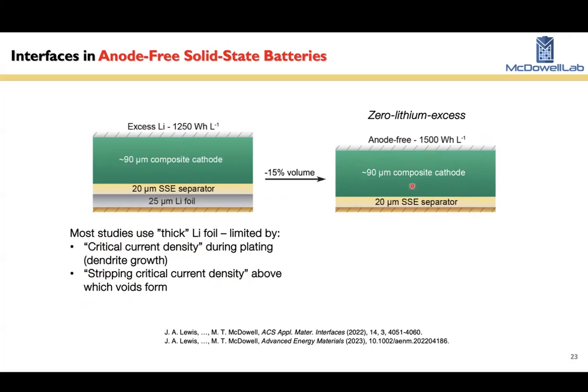And on the first charge of your cell, you move your lithium ions down to the anode and you reduce them and plate out lithium metal on a current collector. The reason why you want to do this is because it can result in higher energy density. You have minimal material at the anode, and so it's commercially very attractive. So the question we asked is, if we move from this scenario to this scenario, we're just getting rid of lithium. How does this affect behavior, and what sort of limiting mechanisms apply to these sorts of cells